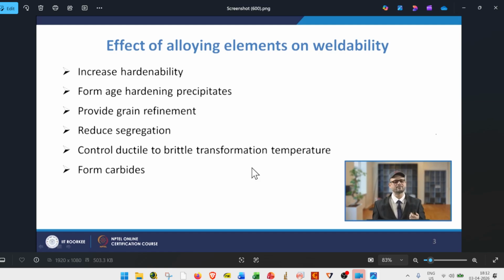So what are the effects of alloying elements on the weldability? If we have an alloy material which has certain alloying elements, what effect does it have on weldability? First, it may increase the hardenability. If certain elements are there, which contribute to the carbon equivalent, like chromium, nickel, and so on, those may tend to promote the formation of the martensitic phase. So that will result in increased hardenability.